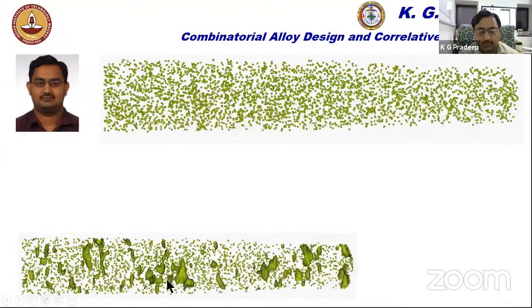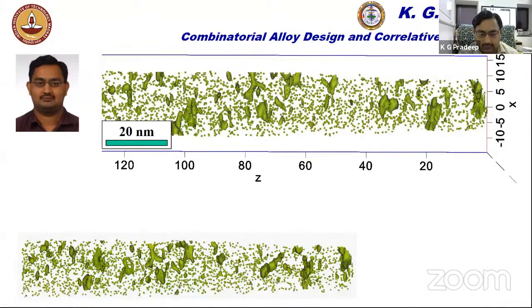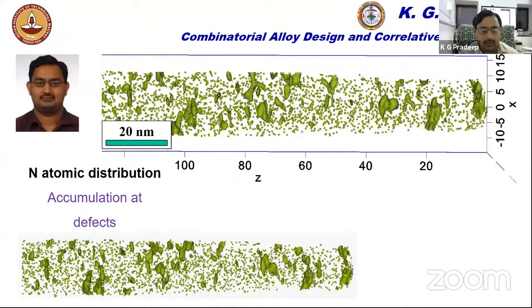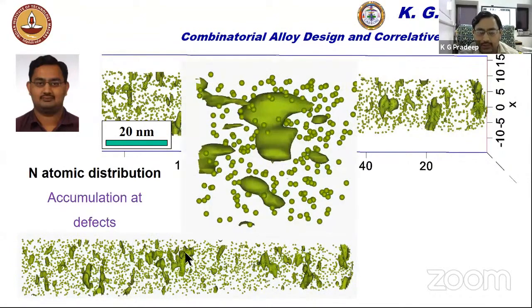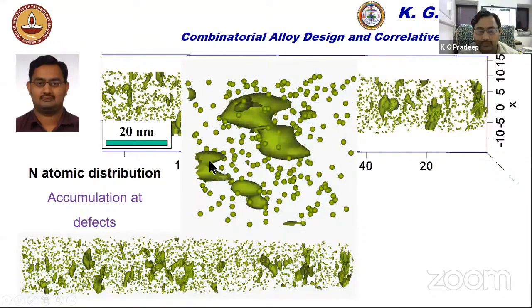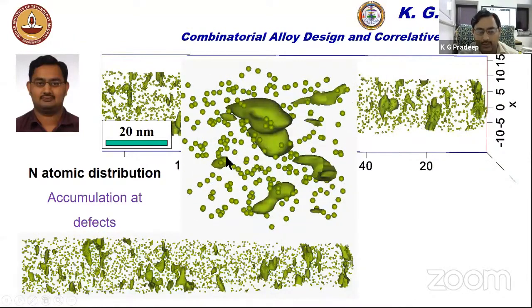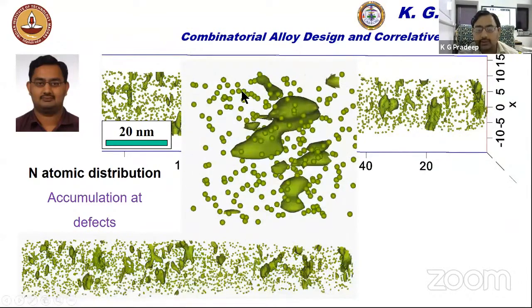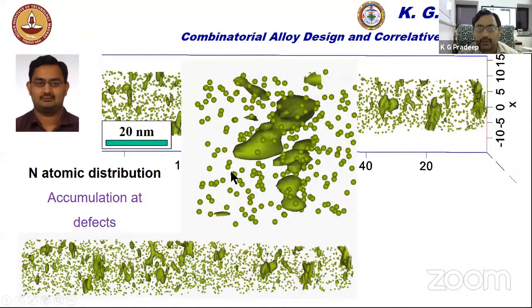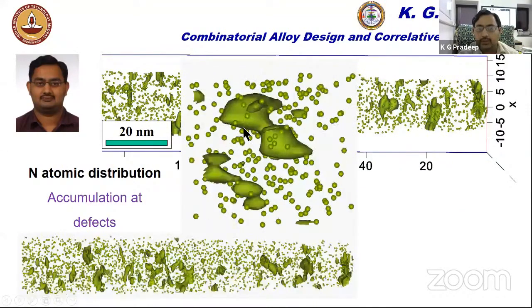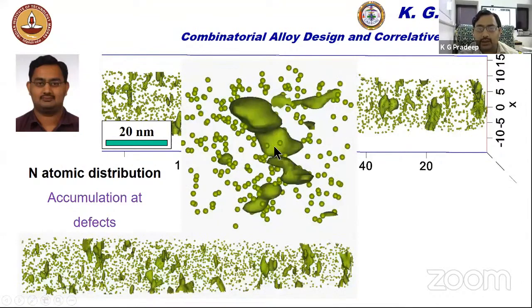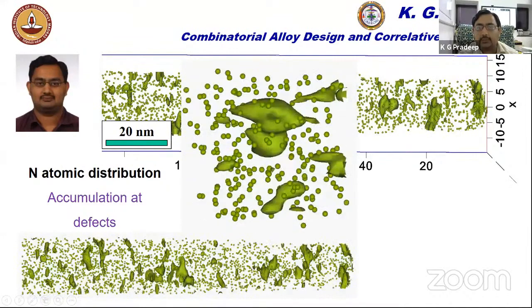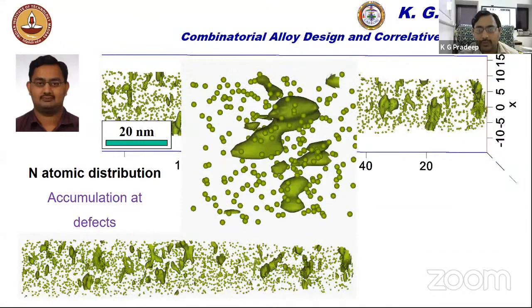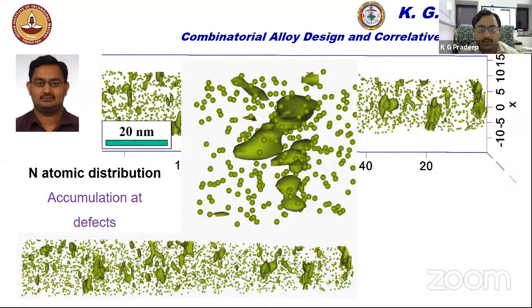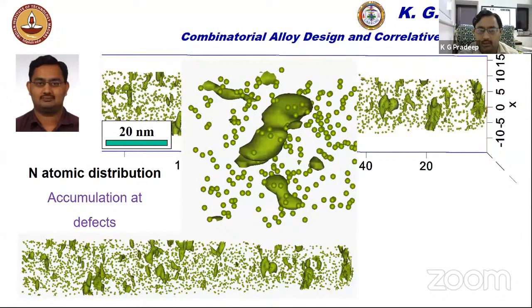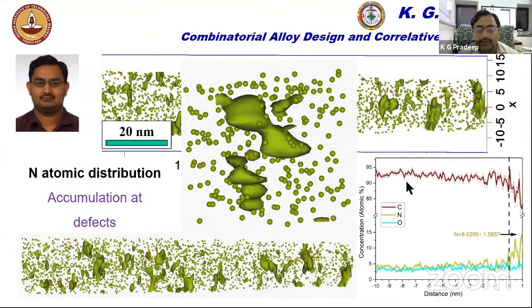We can now select specific regions out of these clustered domains where the nitrogen atoms get accumulated. And now we can see, in a highly magnified view, a three-dimensional distribution of the nitrogen atoms in the matrix, as well as clustering of atoms into local defect sites. And furthermore, we will be able to even quantify how much of this nitrogen has gone into the defects, which are primarily responsible for the behavior or the conductivity of this diamond, with respect to your nitrogen concentration.